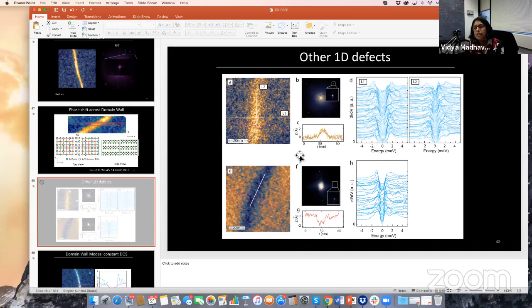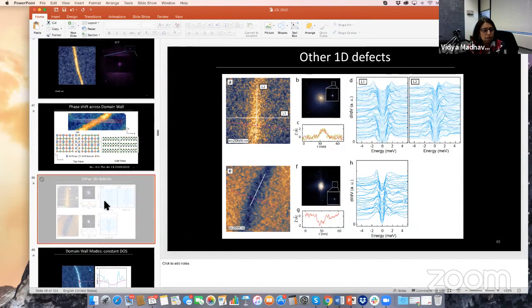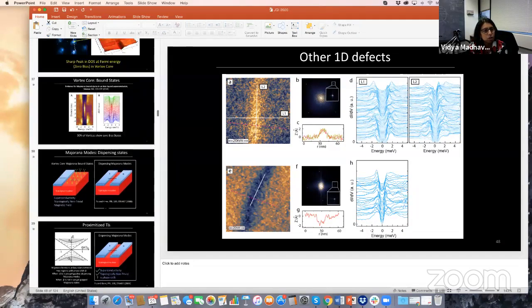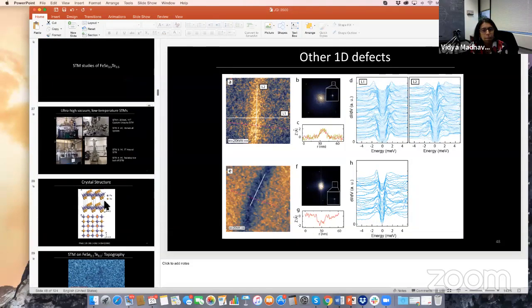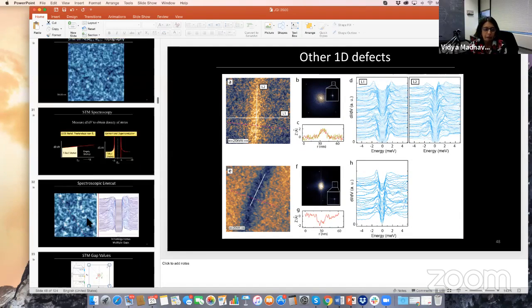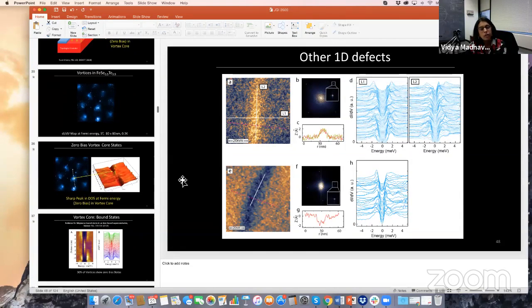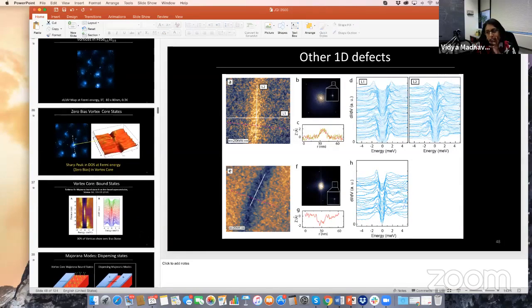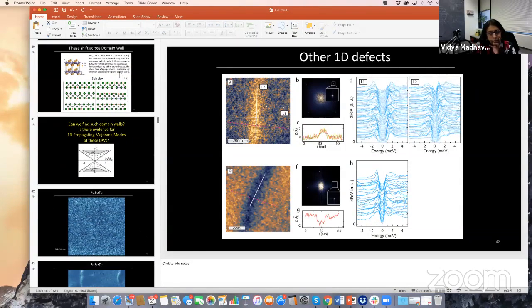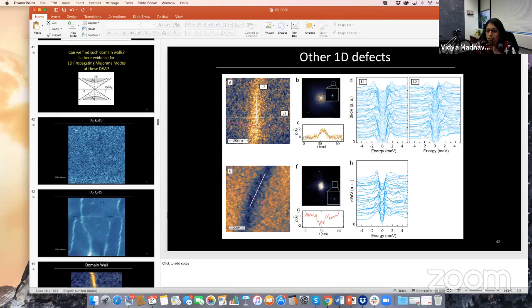Here's one. So what you would see is that this is a 1D defect that's not a pi phase shift. And you see a nice superconducting gap that goes to 0. It's just that the gap magnitude gets smaller. So that's one thing that happens. And then another thing that could happen is that inside the superconducting gap, we see just sharp peaks in the density of states at various energies in a particle-hole symmetric way. So those things happen. And so it's only when you have this pi phase shifted domain wall that we see this peculiar feature, which is the flat density of states. Yeah, that's just an experimental observation. So, have I answered your question?